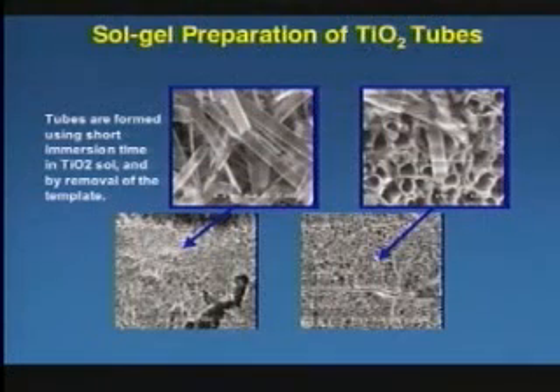So this is an alumina membrane. Here are the etching of the pores. Here's the straws that we get when we coat the sidewalls with TiO2. We release the alumina from that, and then you can pack them, and you can see this is an all-inorganic, robust membrane of a metal oxide, TiO2, that by itself, if we shine light on it, as I told you, with catalysts on either side, would almost, unassisted, split water and act as the separation membrane.